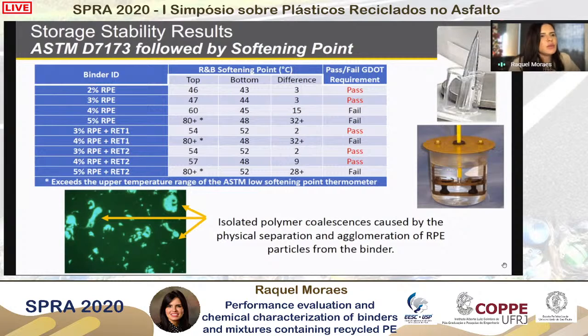And you can see that we use a criterion that is defined by the Georgia Department of Transportation that says that the difference between top and bottom samples after softening point cannot go over 10 degrees. And we can see that among all the samples that we evaluated, we only have 5 that pass the Georgia DOT requirements. And please keep in mind that we are not saying that by passing this test, we have a favorable blend. No, this was just the initial screening so we can move forward on the evaluation of these binders modified with the recycled plastics.